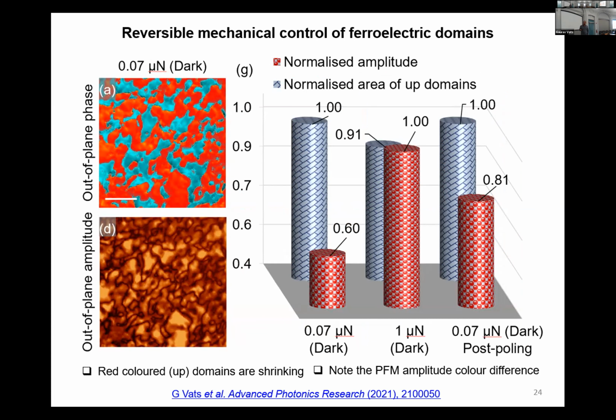But when we look at the amplitude, basically the piezo response of the material, it was somewhere here. It increased when I increased the mechanical load, and on removing the load, it was supposed to come back here, but it is here, which is higher than the pristine state. That means my material is not damaged with this mechanical stress. There is no change in the surface. That means we are not damaging our material. So our finding for this one is that we can mechanically pole the sample even in the absence of light. Then I decided to shine light on this.